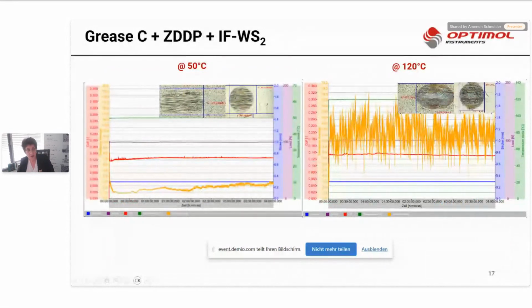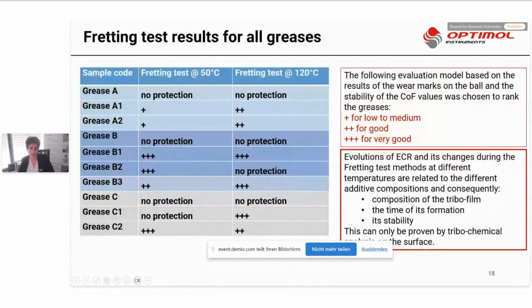This grease is also very nice. I want to just show you one example for this series. Grease C, ZDDP, and this nanoparticle has also good results at 50 degrees. Very nice result at 50 degrees Celsius, and also nice friction value at higher temperature, 120, but again, a little bit higher wear values because of temperature and ZDDP.